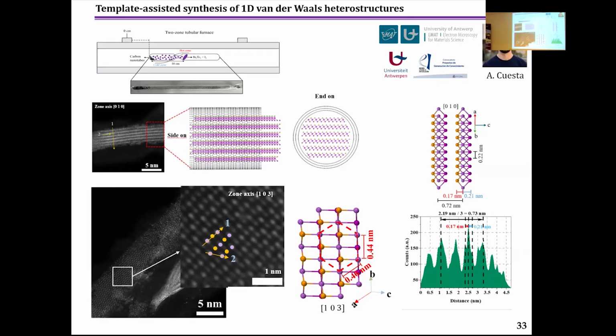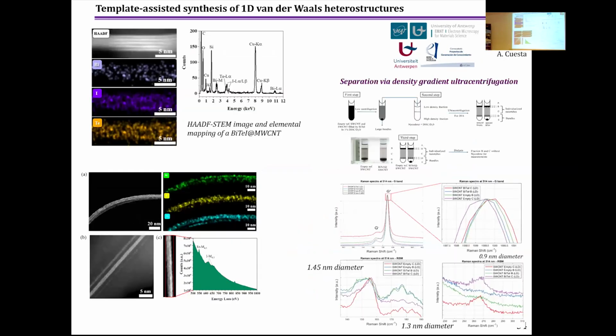Importantly, there is the encapsulation of bismuth tellurides. In this case, we prepare this material by using a transport agent, iodine, in order to facilitate the migration of bismuth telluride inside the tube, the sublimation, and also the deposition inside the tubes. This material was also characterized inside the carbon nanotubes, and in this case we obtained layered bars whose structure matches the structure of the material in bulk. And then we encapsulated the material in single-wall carbon nanotubes.